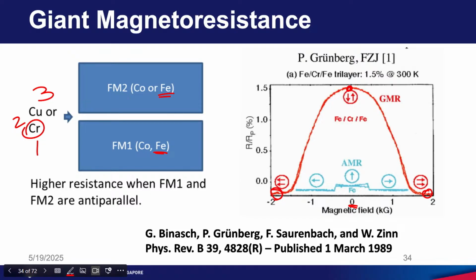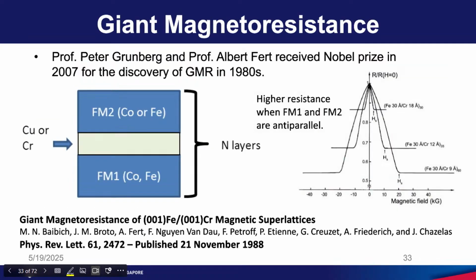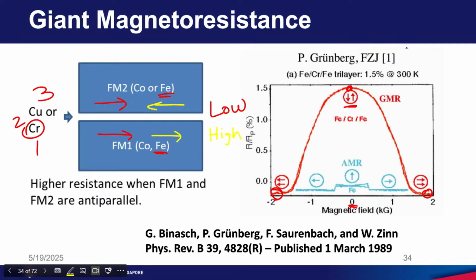In their paper they clearly show what happens. At 0 field the two magnetizations are anti-parallel, and at very large field they are parallel to each other. All these results indicate that when you have two ferromagnetic layers separated by some spacer, if the magnetizations are parallel, you have low resistance, and if they are anti-parallel, you have high resistance. Both results are similar, only the sample structures are different between the two groups. Another difference is that this observation was carried out at 4 Kelvin or some low temperature. I do not remember the exact temperature, but somewhere at low temperature, whereas this observation from Peter Grunberg's group is at 300 Kelvin.